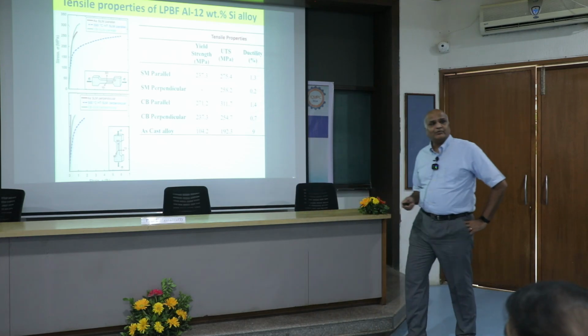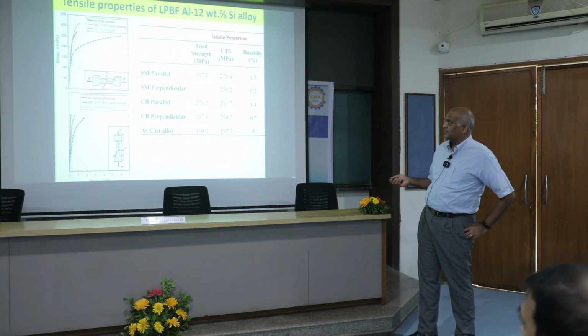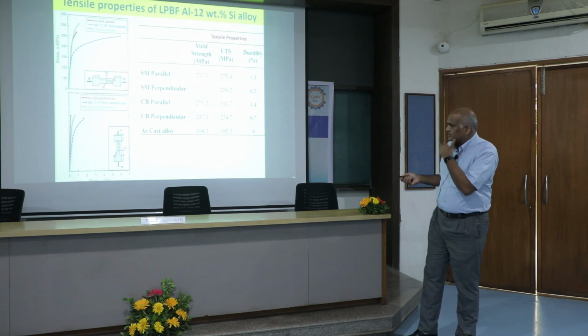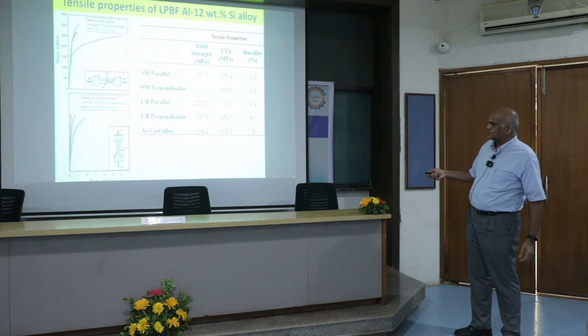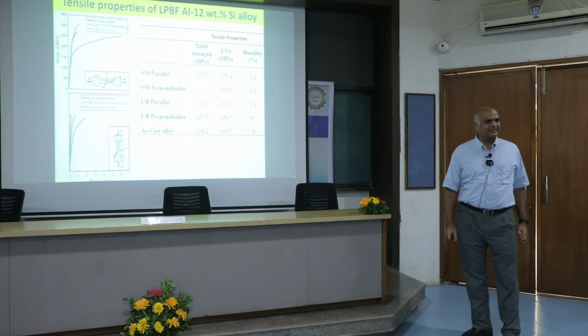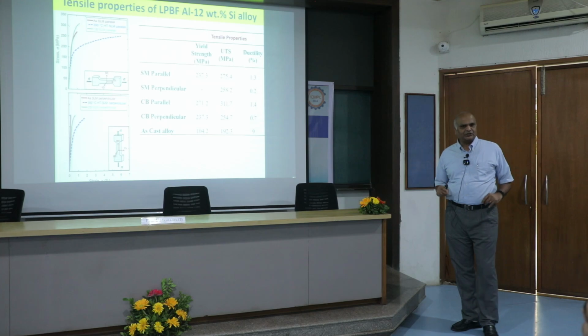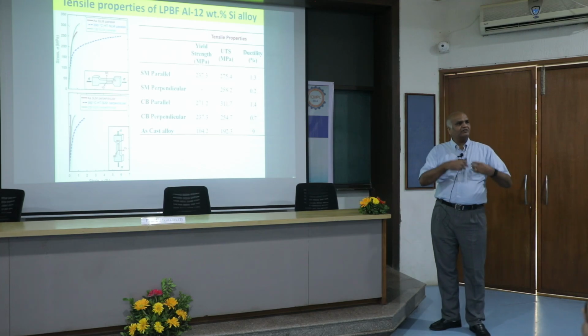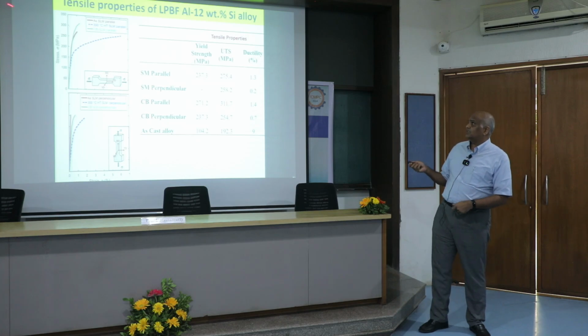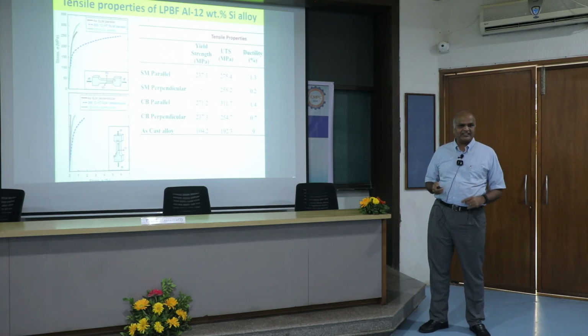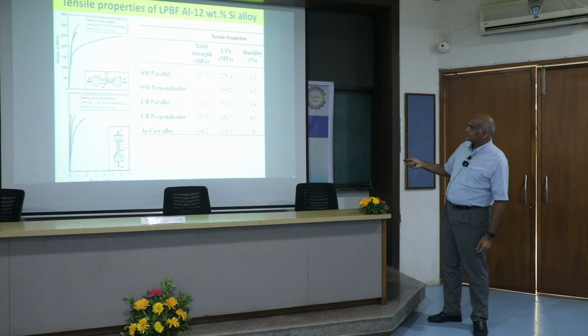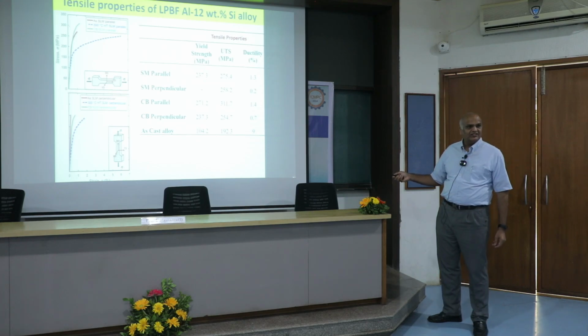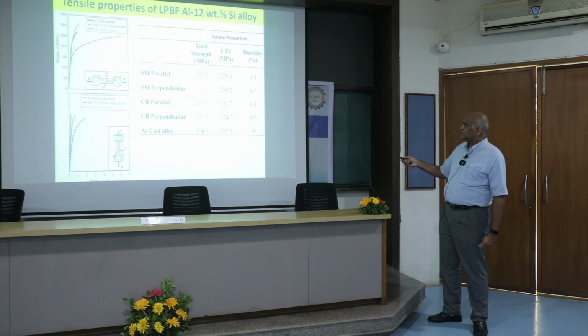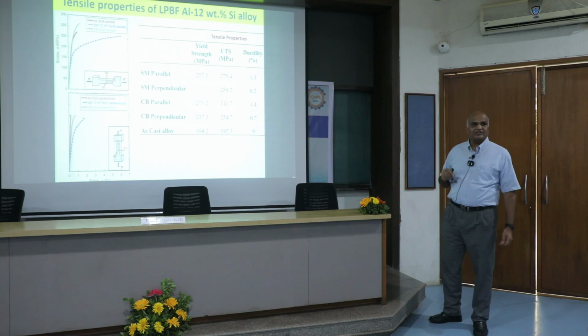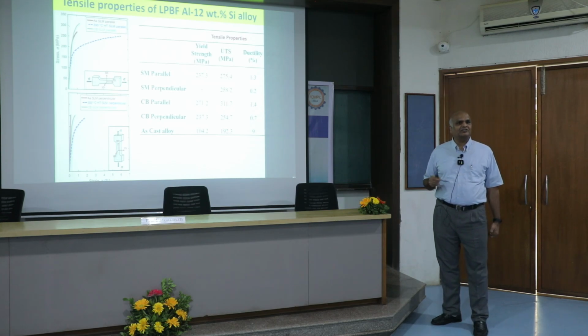So when we looked at the mechanical properties, we did tensile testing, parallel and perpendicular, etc. What we noticed: the same alloy, if you take it in the cast form, its yield strength is 100 MPa, UTS is 200 MPa, and it has about 10% ductility, right? So this is why it's used. So we take the same alloy, make a powder of it, and then use basically laser powder bed fusion, right? This 3D prints the alloy. Okay, so you see that the yield strength has gone up a lot compared to this, more than 100% increase, right? UTS also has gone up a bit, but ductility has come down. Okay, so this material now looks very brittle.